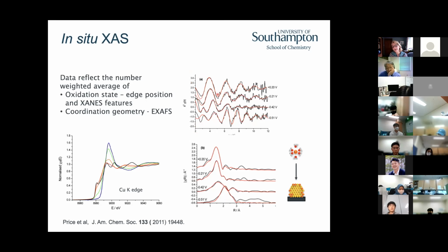So what this is telling us is that in the first case, the coordination is quite short distances, longer period oscillations. We can tell that the neighbors are low atomic number, so probably the oxygen atoms of the water. Those neighbors are low atomic number, so the backscattering is very damped, and we don't see as much of it. This really tells me I have copper in a low Z, a low atomic number coordination environment, with the distances being quite short.